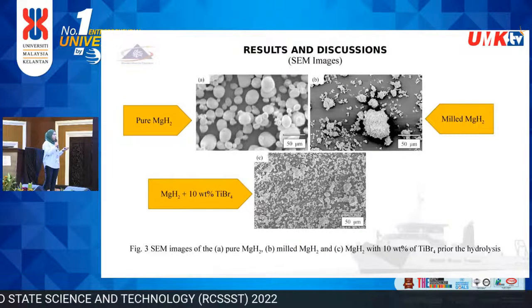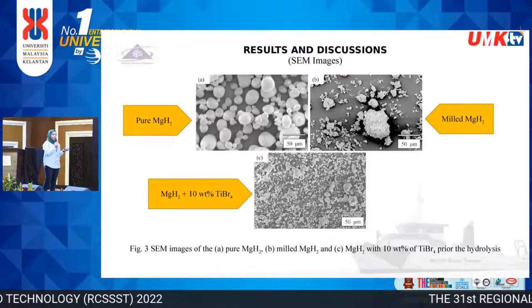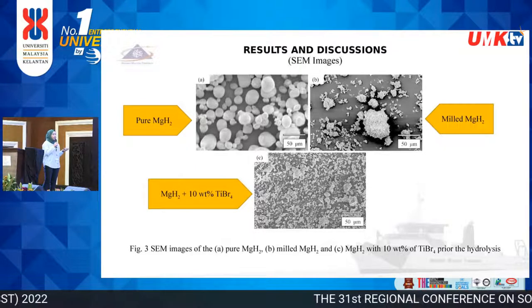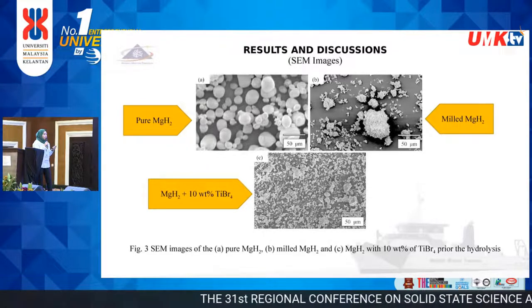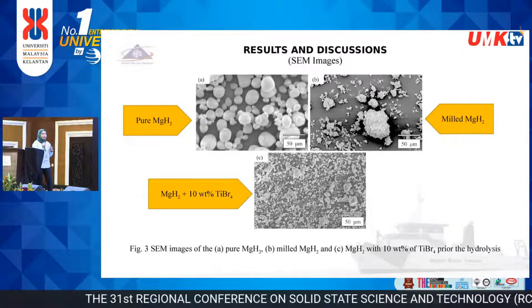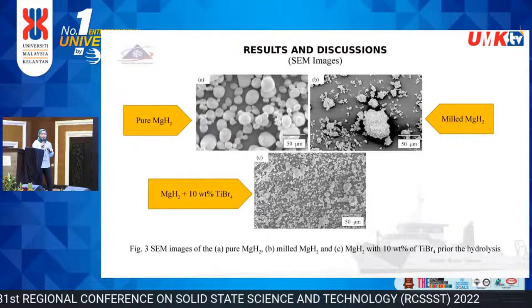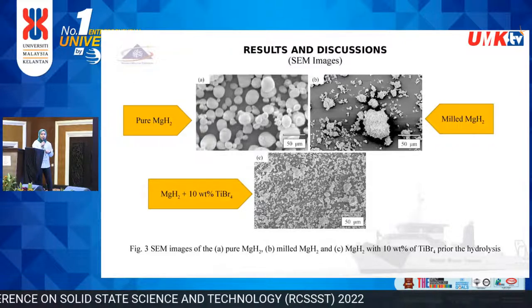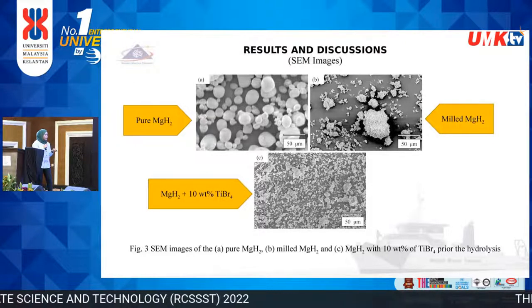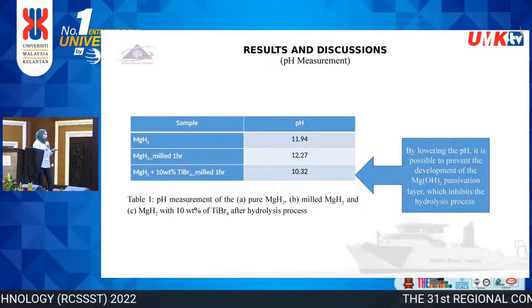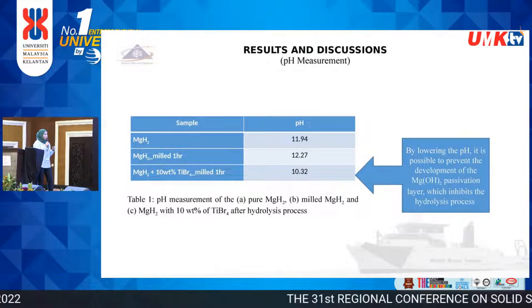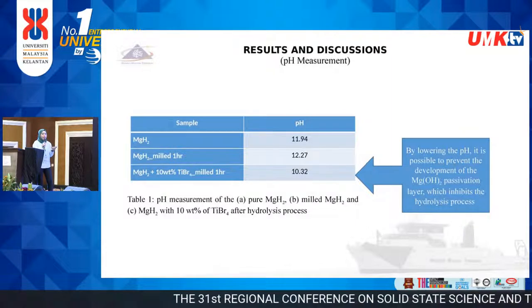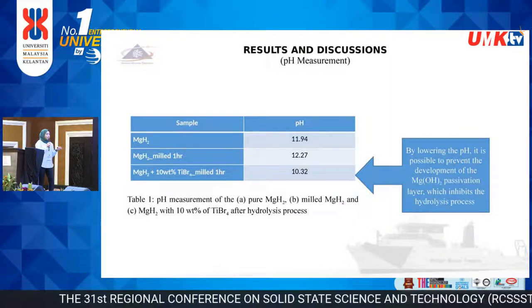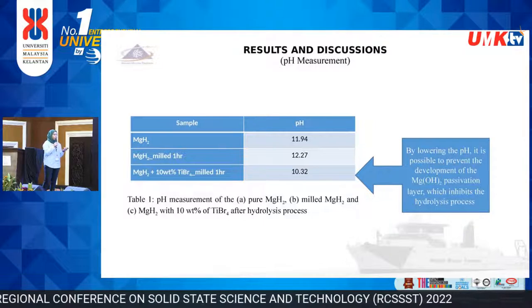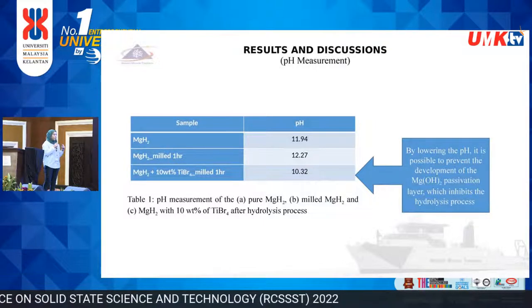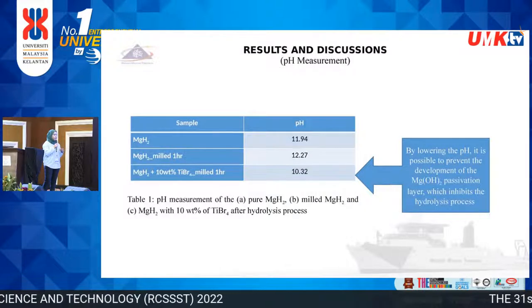Okay, so these are the SEM images for the samples. It shows that when adding catalyst to the samples, it has effectively reduced the size of the particles. When the size of particles is reduced, it will increase the effective surface area for the hydrolysis to occur. For the pH measurement, the pH has reduced to 10.32 for samples with the addition of catalyst. So by lowering the pH, it's possible to prevent the formation of the magnesium hydroxide passivation layer that inhibits the hydrolysis process.